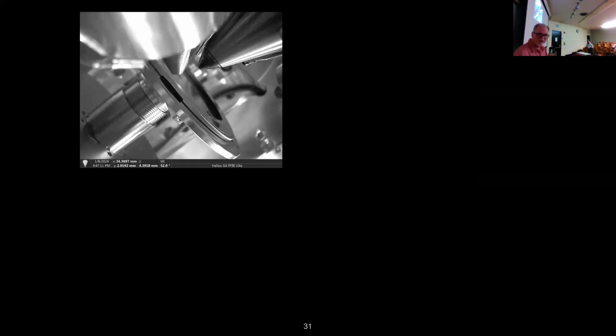So here's another view of our gasket. You can see there's a hole when we're tilted to 52 degrees. We're now normal to the ion beam. There's probably around 200 microns of spacing between the sample and the very expensive electron lens. So we really have to make sure that we are on top of setting eucentric height. So eucentric is a point about which you can tilt and you do not have image translation. I will probably hate myself for saying this, but take out your phones, people, if you have them, and look at a spot. When you can find a spot where you can tilt and not have a translation, that's eucentric.